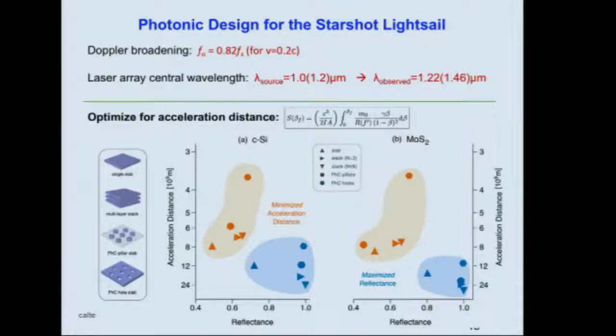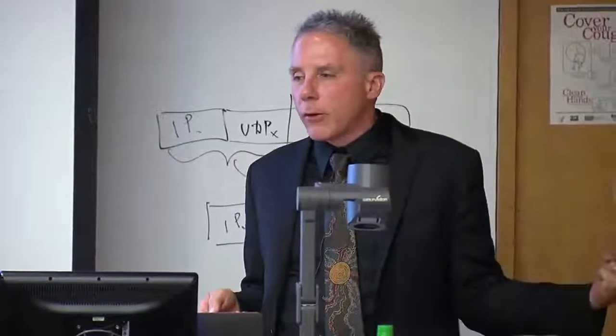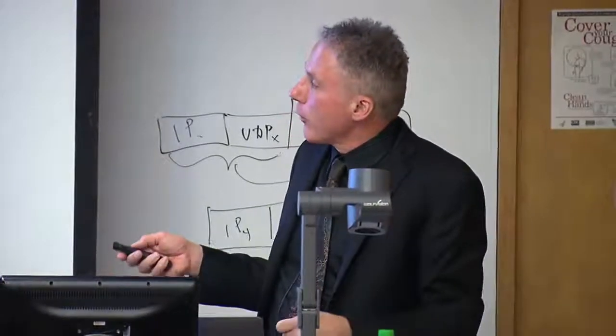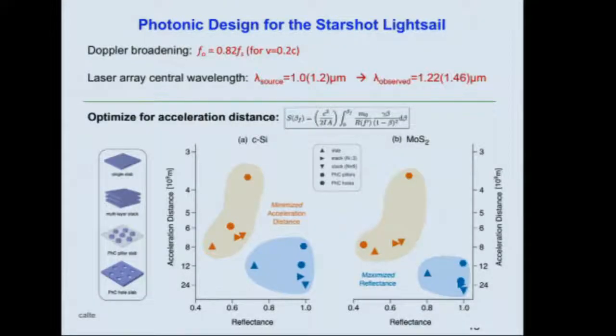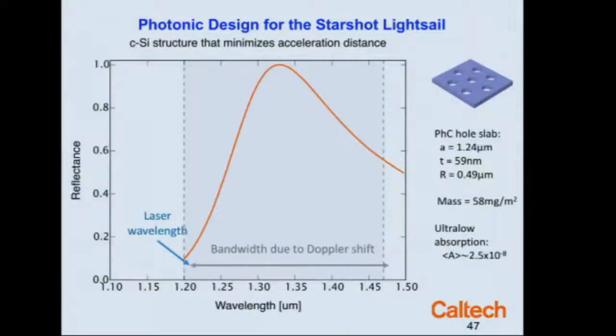And the reason is very simple. By putting holes in the photonic crystal, we take away some of the weight. And so it turns out we can give up a lot of reflectance in our design optimization in favor of getting rid of the weight. And so that can reach 0.2C according to this analysis in even less than 1,000 seconds. Surprisingly, you would have thought perhaps the optimal one would have a reflectivity of 99.9% across this whole band. This is the reflectivity of the optimal structure. By giving up the weight, we were able to, the optimal solution told us we could sacrifice.